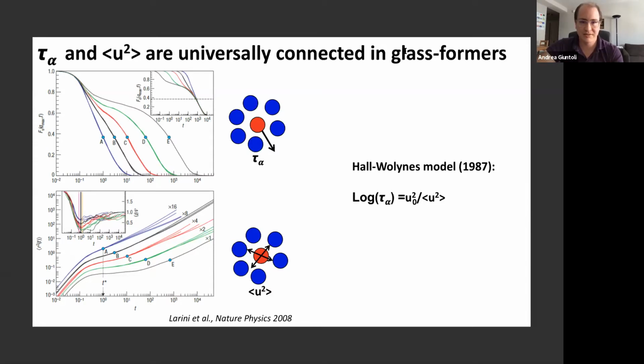Now, this idea is not exactly new. It was in the air since 1987, where there was a model saying that the alpha relaxation time is inversely related, with an exponential law, to the energy required to escape the cage. Because if you have more energy, it's easier to escape the cage. And so the alpha relaxation time will be lower. And this energy can be estimated with the Debye-Waller factor, because that measures how much you're moving in the cage. But that idea wasn't really working well for a lot of systems besides high temperature liquids.